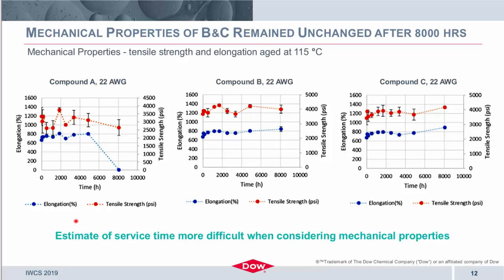Thus, it makes estimating a service time based on this data very difficult when you just consider the mechanical properties of these samples, because they are performing and are stabilized out to beyond 8,000 hours or significantly longer times than we measured in this study.